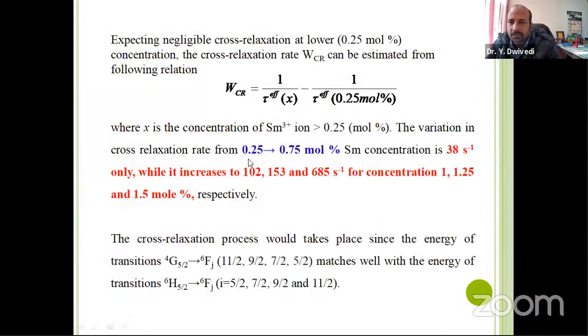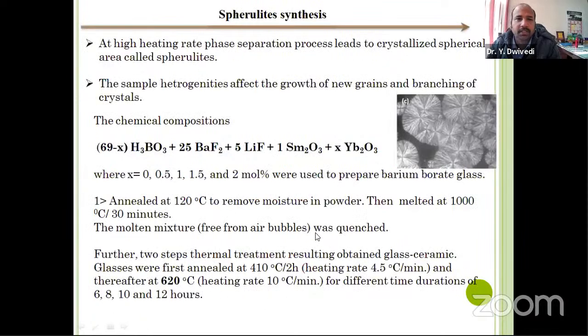So the cross relaxation, meaning the energy transfer between identical ions, we tried to estimate, and from the very lower concentration of 0.25 mole%, we see that it increases from 38 per second to 685 per second, and this is due to several transitions having energy matching conditions.